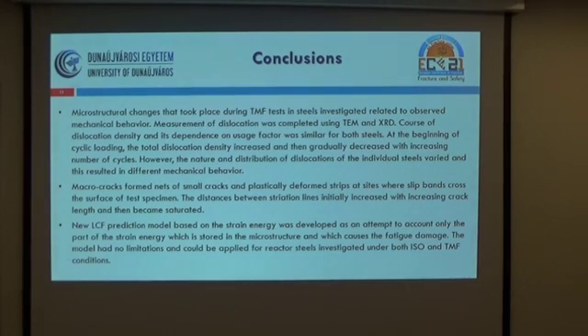Quickly the conclusions. The microstructural changes are related to the observed mechanical behavior. We performed dislocation density measurements, both by calculation on the TEM pictures plus with X-ray diffraction, and the course of the dislocation density and its dependence on the usage factor was similar for both steels. At the beginning of the cyclic loading, the total density increased and then gradually decreased with increasing number of cycles. However, the nature and distribution of the dislocations of the individual steels varied, and this resulted in the different mechanical behavior of the two types of steels.